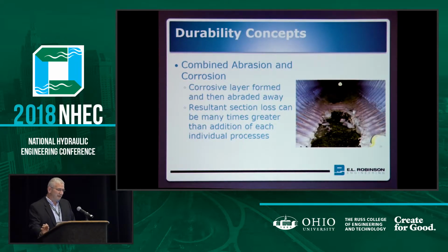The other interesting thing is that when we talk about corrosion and abrasion, you always have to think about them as a combined process. If you look at abrasion by itself and corrosion by itself, and then add those two together in terms of the longevity of the structure, those two acting in concert is much, much greater than those two acting independently of each other. It's actually exponentially greater. And so you can see extreme degradation of pipes when you have high abrasion and high corrosion.